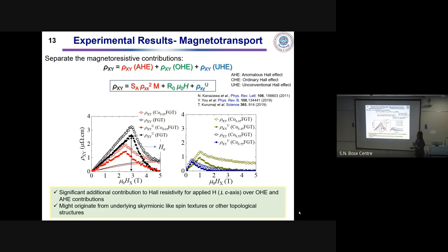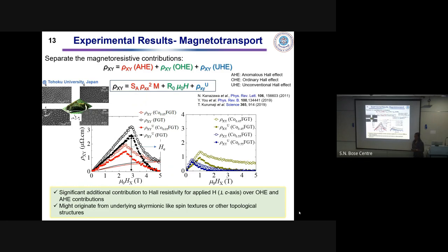However, we further extended our study and performed magneto-optical Kerr imaging in collaboration with the Tohoku University. What we observed from the MOKE data is that when the magnetic field was applied in this direction, we could see stripe-like domain patterns of alternating contrast, and these stripe-like labyrinthine domain patterns are usually observed in systems having uniaxial magnetic anisotropy. However, what was interesting is that within these stripe-like domain patterns, we could see small bubbles present, small circular domains embedded inside these stripe-like domain patterns. And that was present for FGT as well as the doped compound.